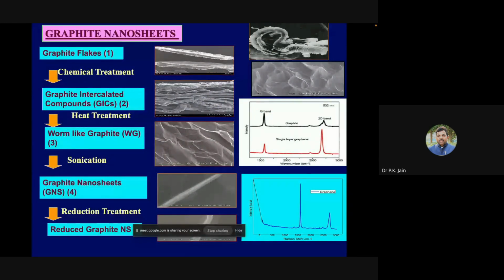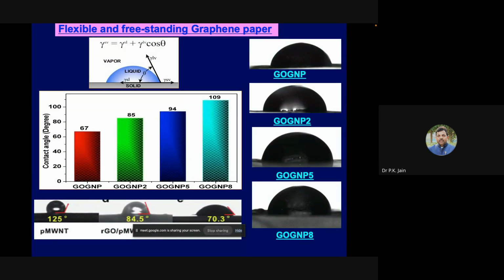So when you are working on graphene and other things, you require a high-end Raman, because normal techniques will not give you an idea about graphene. The disadvantage of carbon research is that everything looks black, whether it is carbon black, graphene or CNTs. You cannot tell just by visual inspection. You require high-end equipment. You can play with the chemistry of this graphene, changing it from hydrophobic to hydrophilic. All those things are possible by different treatments, and the contact angle has varied from 67 to 109.